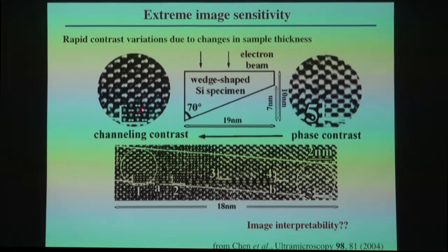Atom columns, well, but how are you going to interpret? If you didn't have the image simulation, what would you make of all this extra detail? And here are actually some simulations. They put simulations inset to the 3 and the 4 and the 5. Here we are going from 3 nanometers thick to 10 nanometers thick, and you have a serious problem with image interpretability. So just because you've got an aberration-corrected microscope that says all of a sudden you've got better than one-eighth nanometer resolution doesn't mean you can put your sample in the microscope and expect to get interpretability to better than 1 angstrom. You had better be worrying about the preparation of your sample.